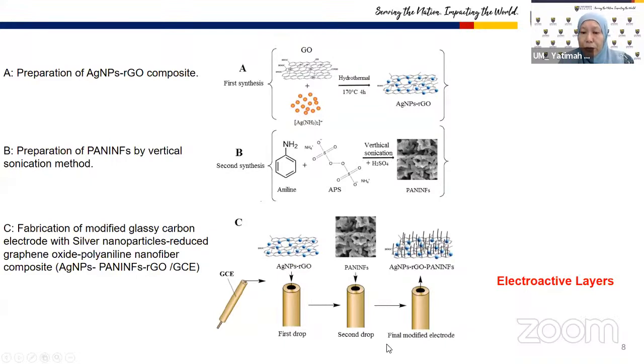And then finally, when they try to do a modified electrode, you can see the reaction between silver nanoparticles and PANI, and they can produce the electroactive layers. So this is what we call the final modified electrode. So we can do different combinations of material to get a final modified electrode. So this is the whole spectrum of understanding before we go deep into one by one, what type of material. But I would like the students to understand why we call it electroactive layers on the surface of the modified electrode, because the bare electrode, the main electrode used, is actually the GCE. On top of GCE, we put another electroactive layer consisting of silver nanoparticles, reduced graphene oxide, and also conducting polymers.